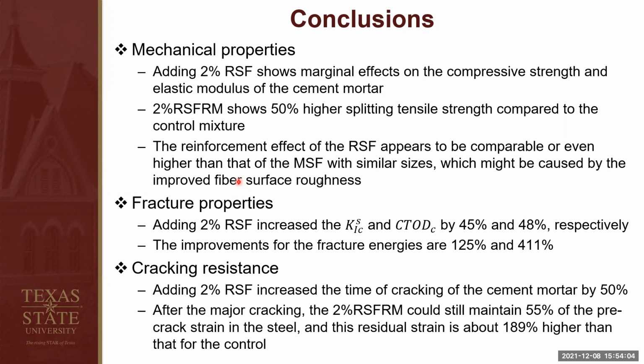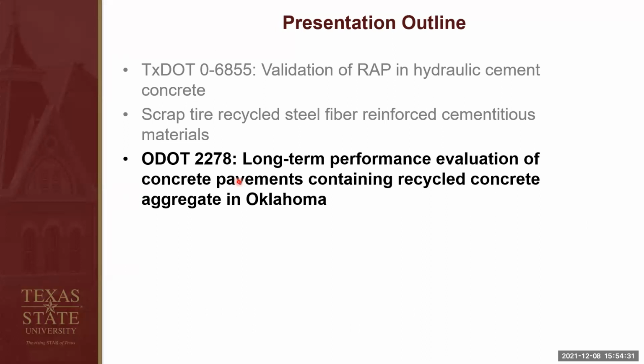For the cracking resistance, adding 2% recycled steel fiber increased the time of cracking of the cement mortar by 50%. And after major cracking, the fiber reinforced mortar sample could still maintain 55% of the pre-crack strain in the steel, and this residual strain is around 200% higher than that for the control. That is my second topic.